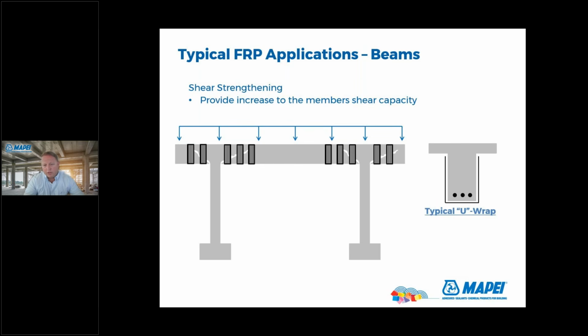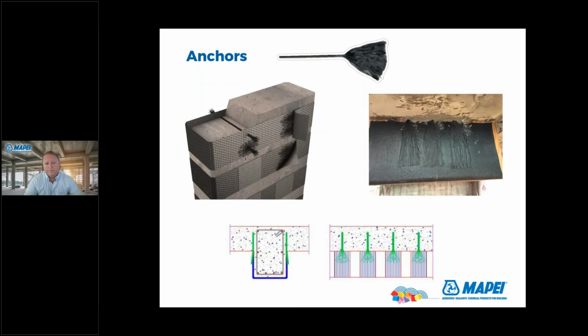Normally you would use some stirrups in the beam in this area. Very similar, you use FRP and do a U-wrap around the beam to increase the shear. Now, anchors are also used, especially in these applications for strengthening beams. We've seen that up at the top.